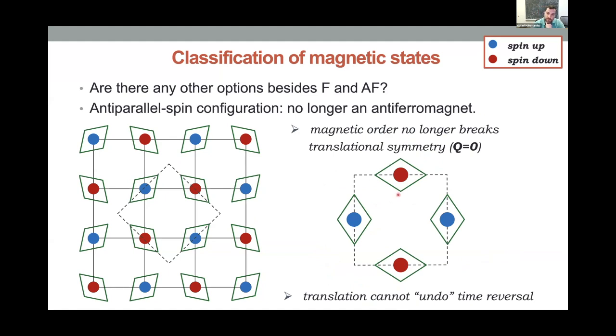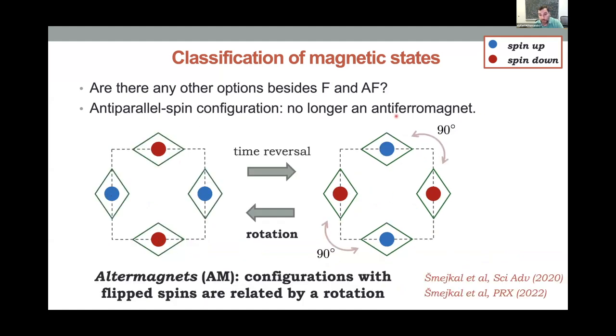So that is not the same as an antiferromagnet. But what you can do is actually do a 90-degree rotation in the lattice, and because of this, you can see now that you recover the same magnetic configuration from which you started. So time reversal combined with rotation is a symmetry, and that is what I classify as an altermagnet. And this, again, I'm sure you heard it in Libor's talk, started back in 2020, formalized a little more a couple of years ago, and continues to evolve.